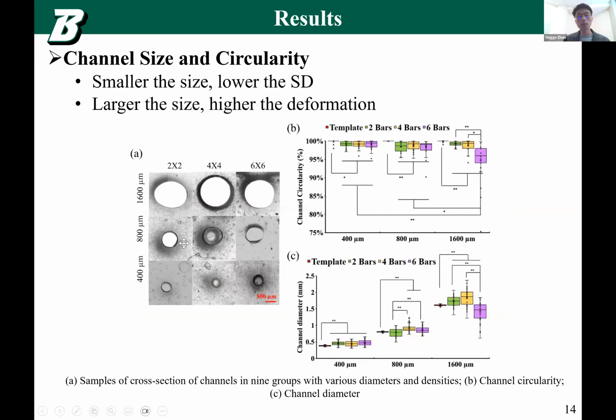And we also tested the size of the channel within the hydrogel, because hydrogel is soft. So if the channel is too big, then the channel will be deformed. And this is also what we found. The 1600 micron has more deformation, and the 6x6 bars also has more deformation. The larger the size, the higher the deformation. And the smaller the size, the lower the standard deviation of the diameter and the circularity.